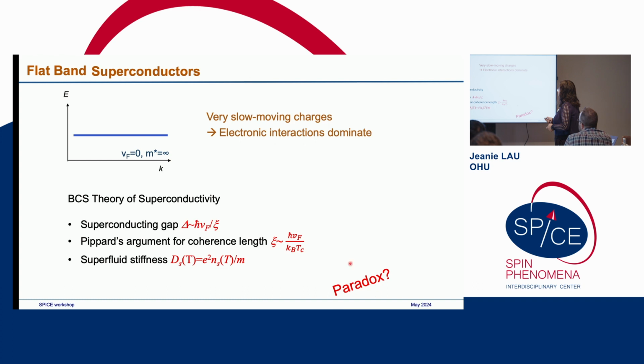So, a little bit more quantitatively, how about in a superconductor? Now we have a flat band, the velocity is 0, the effective mass goes to infinity. If you plug in those numbers into the equations for the BCS theory of superconductivity, for example, the superconducting gap is proportional to the Fermi velocity, and if you use Pippard's argument, the coherence length is proportional to the Fermi velocity. And the superfluid stiffness, which is this parameter which governs the electromagnetic response of a superconductor, really the essence of a superconductor, tells you how robust the superconductor is. It's inversely proportional to the effective mass.